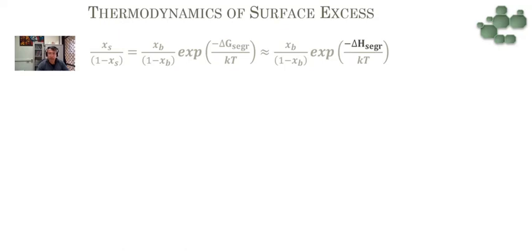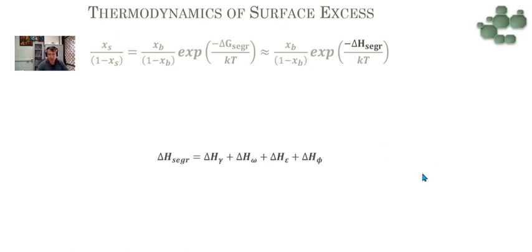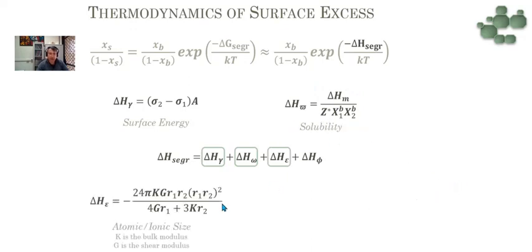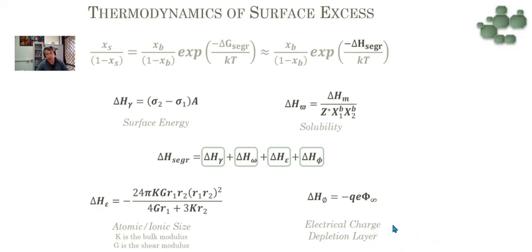Looking at the thermodynamics behind the surface excess: when you have a free energy of segregation, the concentration in the bulk and at the surface are not the same. The free energy of segregation is approximately equal to the enthalpy of segregation. The enthalpy of segregation has four components: the difference of surface energy between the solute and the solvent; the solubility; the difference in atomic or ionic size — when there is a large size difference, segregation is more likely; and the electric charge related to the charge of ions in the system, related to the depletion layer.